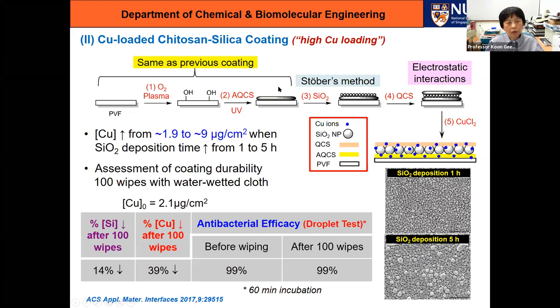And then instead of conjugating EDTA, we grow silica nanoparticles on the chitosan coating using the Stober process. After this is done, we put on another layer of quaternized chitosan to form this sandwich structure. And this gives it stability through electrostatic interactions, because quaternized chitosan is positively charged, the silica nanoparticles are negatively charged. So depending on how long we build up the silica layer, we can change the copper concentration.